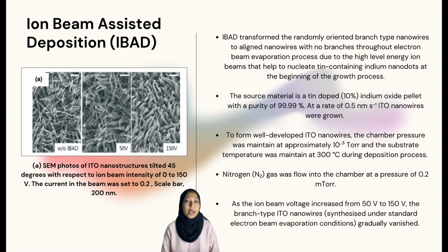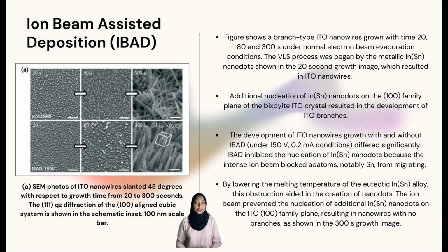To form well-developed ITO nanowires, the chamber pressure was maintained at approximately 10 to the power of -5 torr, and the substrate temperature was maintained at 300 degrees Celsius during the deposition process. In addition, nitrogen gas was flowed into the chamber at a pressure of 0.2 millitorr. We can see that as the ion beam voltage increased from 50 volts to 150 volts, the branch-type ITO nanowires gradually vanish. Next, the figure shows branch-type ITO nanowires grown for 20, 80, and 300 seconds under normal